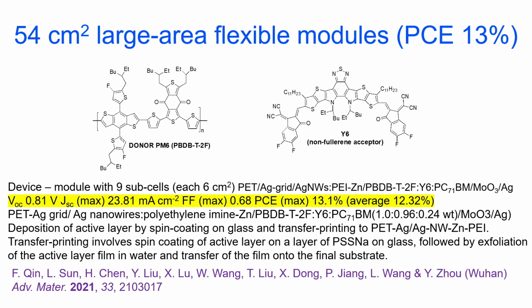Now, since that time, there has been a significant contribution in what I'll call larger area devices. So here's a device here of 54 square centimeters. It comes from this group in Wuhan again, and they made modules, subcells, each of an area 6 square centimeters. So the 54 square centimeters obtained by 9 subcells connected in series. And the combination is a PET silver grid, silver nanowire, and then a polyethylene imine zinc coating, which would make that then the cathode, and then the donor polymer on the left, the non-fullerene acceptor on the right.